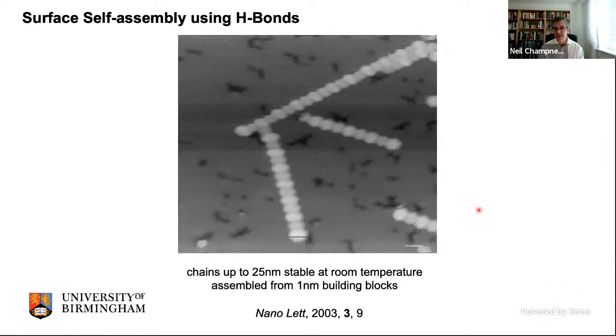And if you look in more detail, this is what you see. Each of these white features, each of these things here, is a single molecule. And those single molecules are arranging themselves into these linear chains. You can measure the distances between the single molecules, and this corresponds almost exactly to what you see in the crystal structure. And you're seeing the assembly of chains through hydrogen bonds in one dimension.